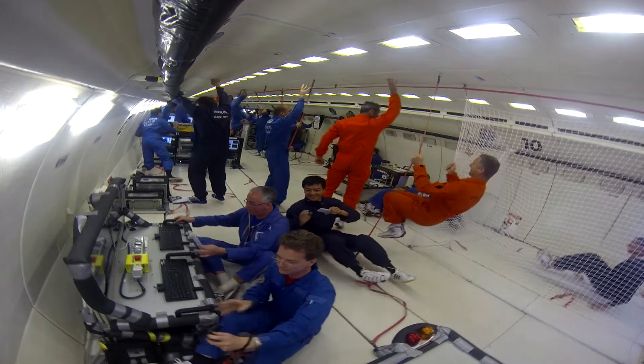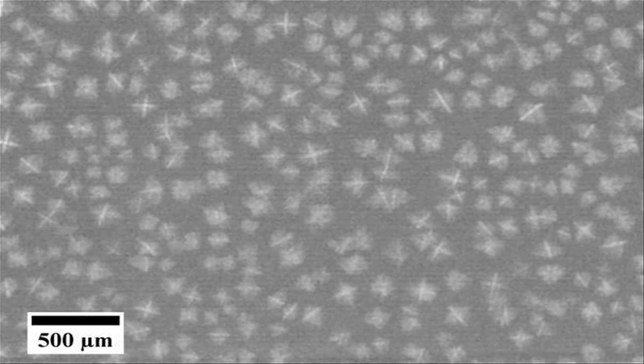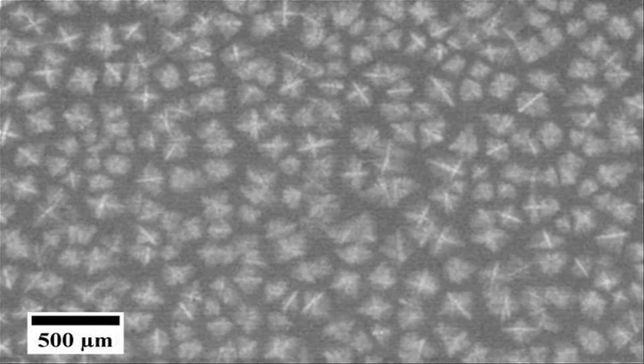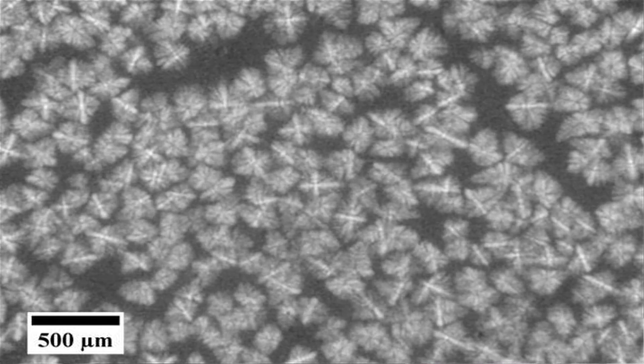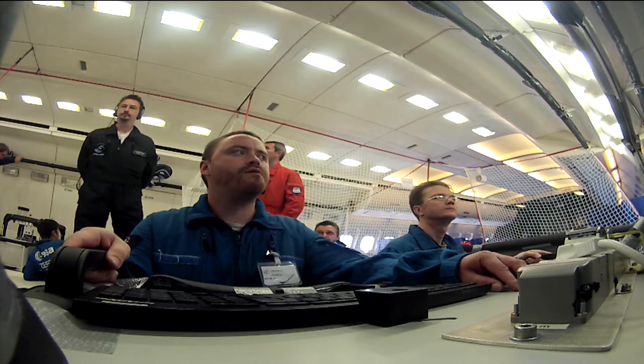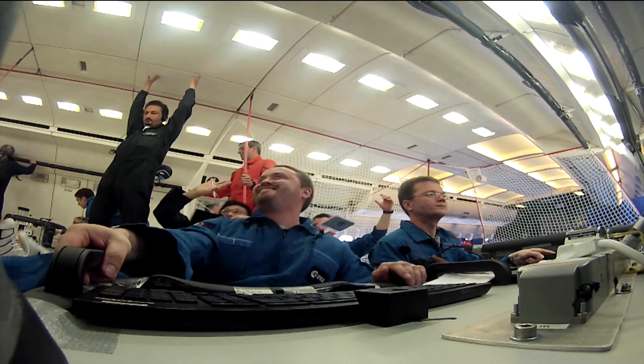During this time we were X-raying the crystals solidifying in a metallic alloy and we could see their suspension in the liquid. Then in 2G, when it hit 2G, they were whipped right out of the field of view. This is part of the in-situ X-ray video of alloy solidification that we use to compare the same experiment on Earth and extract and understand the effects of gravity on solidification of metallic alloys.